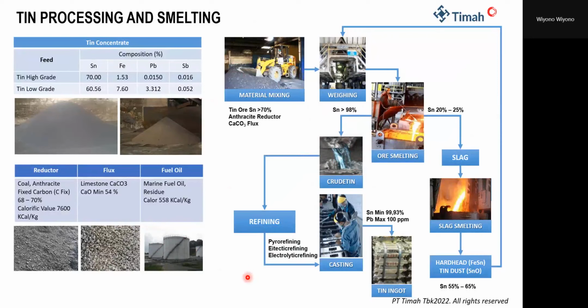In Mentok, we have three processes of refining. The first one is pyro refining. We do pyro refining in kettles. In the kettle, we melt the crude tin, and then we do some processes to reduce the content of iron, copper, arsenic, and many more. But before we do pyro refining, because currently the tin concentrate has a lot of impurities, we do the eutectic refining first. In the eutectic refining, we reduce the lead content.